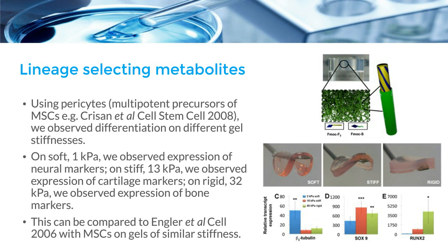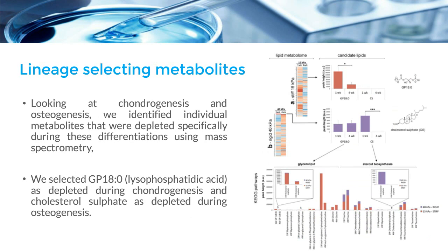So what we wanted to do, the big advantage we had over other groups at this time was that we're using a gel source that were very similar. So we had 3 highly controlled rigidities, and that's really important. Using many material systems, controlling rigidity or stiffness with good level of control is quite tricky. With the Biogelx gels, it's pretty straightforward. But because the gels are synthetic, and the only thing that's changing is the fiber density of the peptide fibers, actually they're chemically very similar.